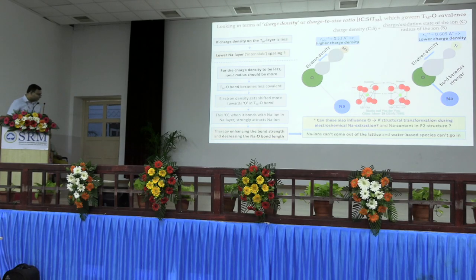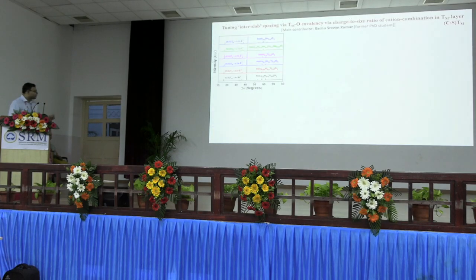So we can see that. Now later we will see that we can use the same concept to develop P2-type structure with a higher sodium content. As I said, it's very important to have the P2-type structures actually being used. So now to improve the air-water stability, study the effect of variation of charge to size ratio of the cation combination in my transition metal layer.